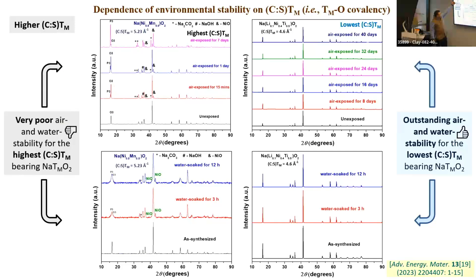The ones on the top are XRDs taken after different intervals of air exposure. One can see for the cathode material having the highest charge to size ratio, even after 15 minutes of exposure in air, it has started forming the impurity phases and the structure has started changing. So it's highly unstable in air. By contrast, the material having the lowest charge to size ratio among all is stable even after 40 days of air exposure. No change at all can be seen from the XRD.